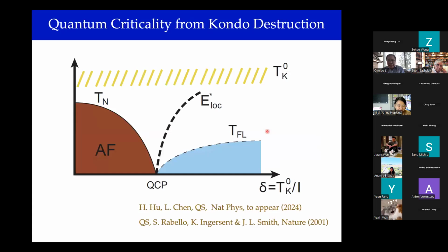And to realize T-linear resistivity in these extremely clean systems, perhaps among the stoichiometric, perhaps among the cleanest of the strange metals, one would need to go beyond the description that invokes antiferromagnetic fluctuations, because that leaves much of the Fermi surface intact. So the theoretical consideration that we and others have done is to invoke the critical destruction of the Kondo effect, which is characterized by this E-star scale collapsing to zero from the paramagnetic side. And that goes to the same place where the symmetry breaking order, in this case antiferromagnetic order, the Néel transition line, terminates in the zero temperature limit. So there's not only the fluctuations of the Landau order parameter, but there's also the destruction of the Kondo effect.